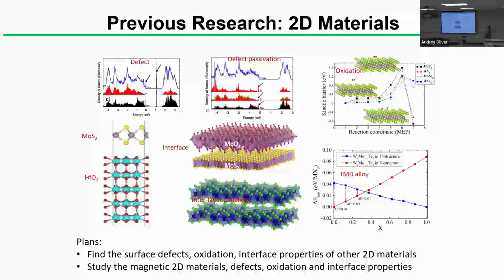We also look into oxidation of the surface. For example, oxygen molecule comes in and absorbs here. What's the energy? What's the kinetics, right? So in this example, molybdenum disulfide, very high kinetic barrier. That's why molybdenum disulfide is stable in air, right? But if there are defects, then it's a different story. If there are sulfur vacancies, then oxygen will absorb there easily. Okay, we can also make alloys. We can mix different 2D materials and tune electronic properties, making metallic to semiconducting, open a gap, or if it's semiconducting, we can change the gap as well with a different composition.